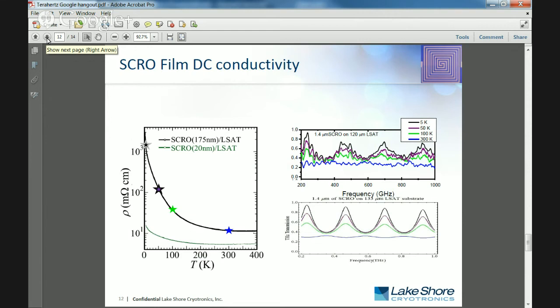And so we've done some corresponding electrical measurements on these thin films, that's what's shown on the right. And so if we just take the DC values, this is just the electrically measured DC value of the conductivity, and put that into our model, we're actually able to reproduce this temperature dependent change in the etalon feature of the Terahertz spectra. But what we found actually goes a little bit farther.